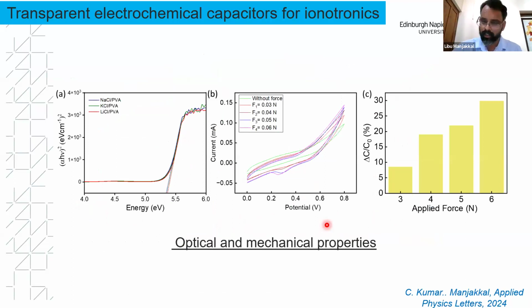Then we measured its optical property and also the mechanical property, as you can see from the variation of the band gap energy of these devices. In such a transparent electrochemical capacitor, there is a gel electrolyte in between. So we apply an external force on top of this electrode, and when you apply an external force, the gel electrolyte distribution changes and the surface interaction changes. Based on that interaction, we found a systematic variation of the capacitance with the force.